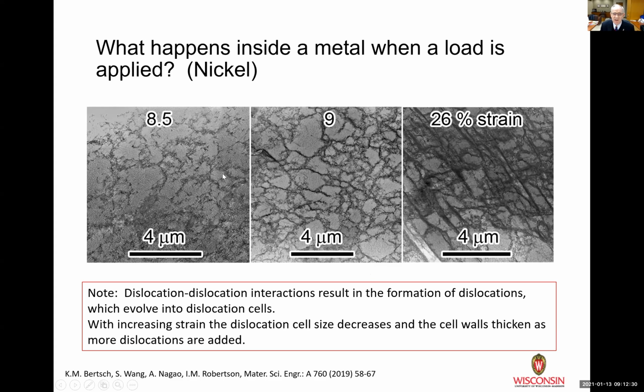You'll see also over in this area, the dislocations have now started to self-organize into a structure. We call that a cell structure. And you'll notice that at 8.5% strain, you get the beginnings of a cell structure, but it's not well formed. If you go to 9% strain, if we could actually look inside these thick black lines that you see, we would find individual dislocations all bunched together in that dislocation cell wall.